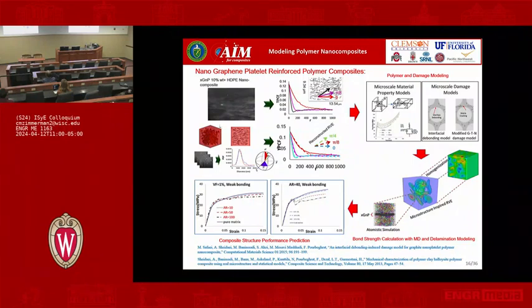Here's an example of nanocomposites: how do we take the data that we collect from an actual part and create a digital twin of it, to be able to generate data so that we don't need experiments? These are nanographene platelets put inside a polymer composite. We use what is called FIB, focused ion beam, to slice this into slices a few microns thin, and you can see there are layers of it. If you look at any of these layers, you can actually see these nanographenes going through.